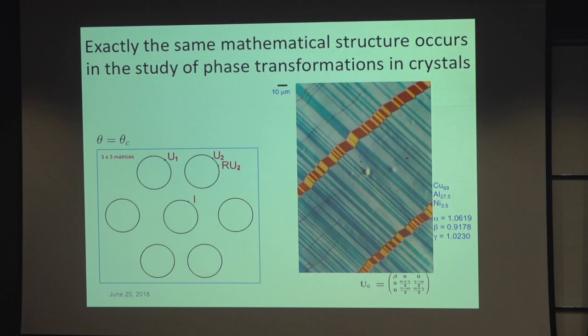If you go in here, you'll notice this is a very unusual situation. You find out that this matrix is compatible with this matrix, and this is compatible with this one, and this is compatible with this one. The normal case is that this would not be compatible back to A. So in that sense, it's very different from origami. But for this material, it goes right back to A. That means all those four interfaces are compatible, and once you realize that, you can make the whole structure.